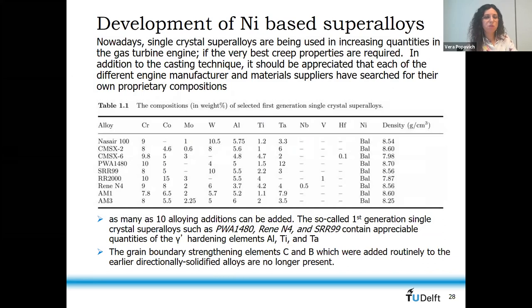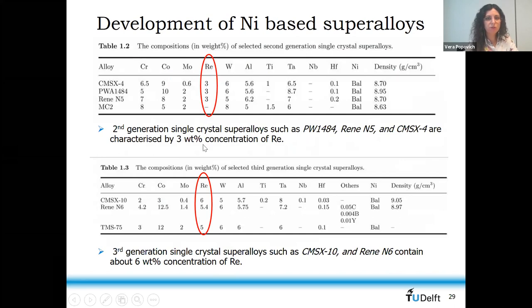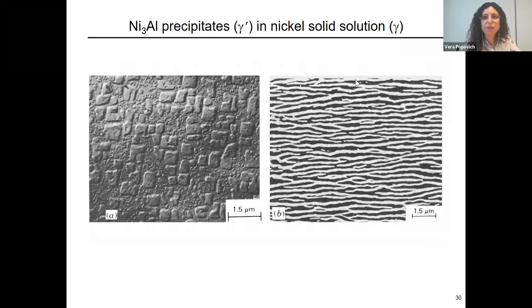with the single crystal superalloys, that's for very high, for best creep properties, the single crystal used in casting technology, still applied. We see that there are more of these kinds of elements. So this is the newer generation, third generation, twice more of rhenium, but up to 6% is used in the more common nickel-based for certain fourth generation. Let's see the question. So this is the single crystal, yeah? So this is SX, so it's a single crystal alloy.